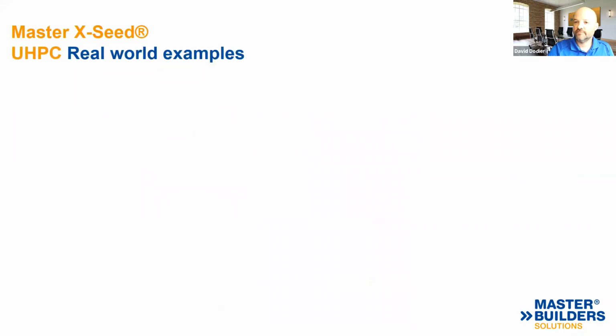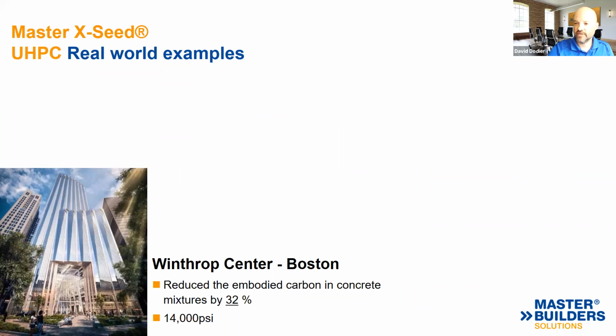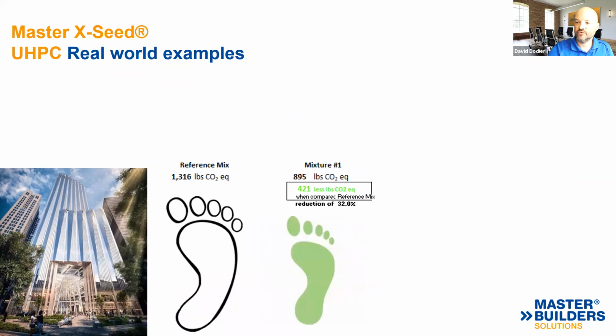I'll give you an example of an ultra high performance concrete. This example is the Winthrop Center in Boston, a 14,000 PSI mix design, where we reduced the embodied carbon in the concrete by 32%. This was using Master X-Seed in combination with some other technologies available in the market, resulting in 421 pounds less CO2 versus the reference mix. The reference mix in this example was taken out of the PCA Design and Control of Concrete Mixtures table, basically referencing some high strength mixes.